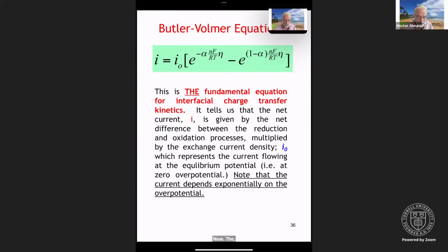Okay. Now, the Butler-Volmer, as I mentioned, is the fundamental equation for interfacial charge transfer kinetics. And it tells us that the net current is given by the net difference between the reduction and oxidation processes multiplied by the exchange current density. I0 clearly represents the current flowing at the equilibrium potential, meaning at zero overpotential, meaning it's the inherent rate of the process when there's no driving force present. The other thing to notice is that the net current is exponentially dependent on the overpotential. It's e to the eta. And that will have enormous consequences when we try to figure out charge transfer kinetics in an experimental context.